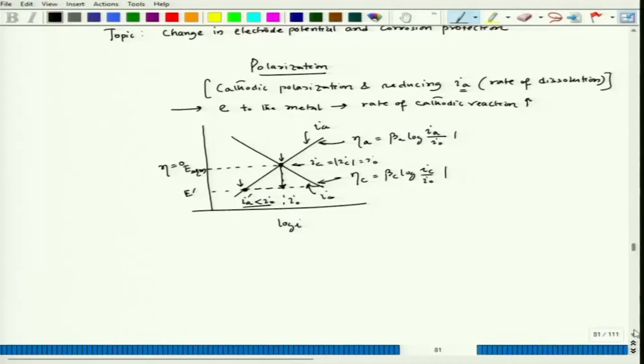So, I could see that if we do cathodic polarization, I can reduce the rate of dissolution, or decrease the current density corresponding to the anodic process. Now, actual corrosion process. So, this is applicable to single redox process. So, this redox process where only M species is there, of course, M n plus ion and M. So, those are the two things and these are basically the same species actually, which is the metal.